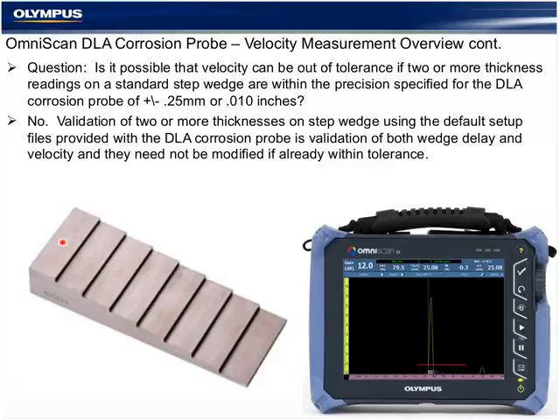The answer is no. If I were to check the step wedge here and here, and those readings are within tolerance, I can assume that the readings in between them are within tolerance, and that is not possible if the velocity were not close and the wedge delay was not accurately entered or predicted prior to setting it on the step wedge.